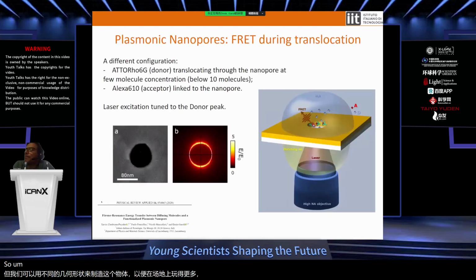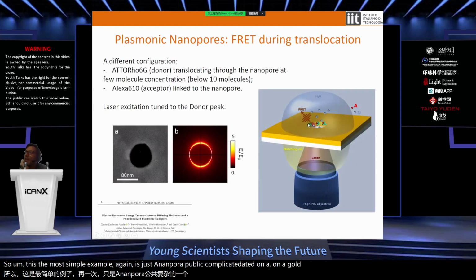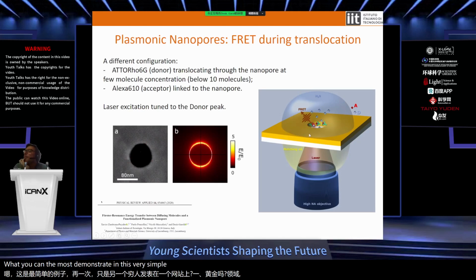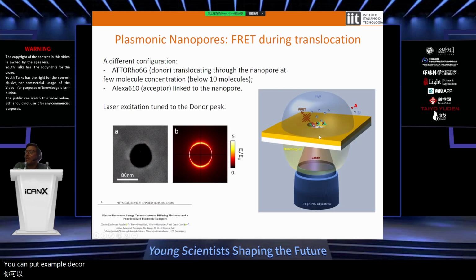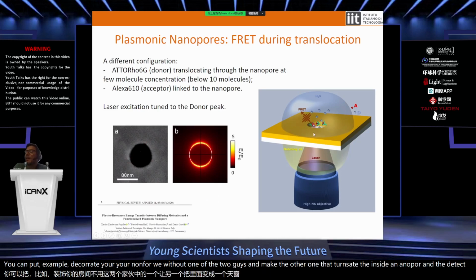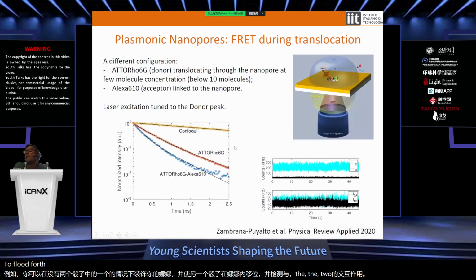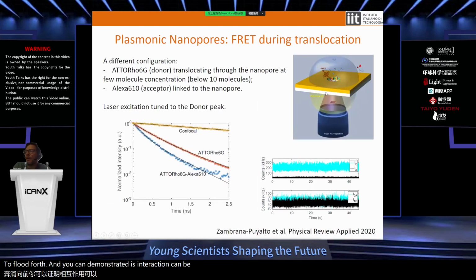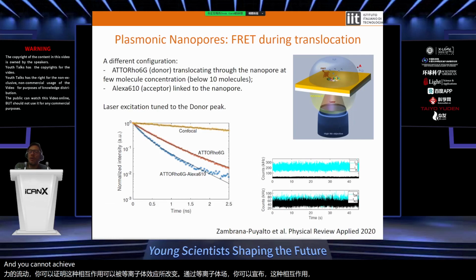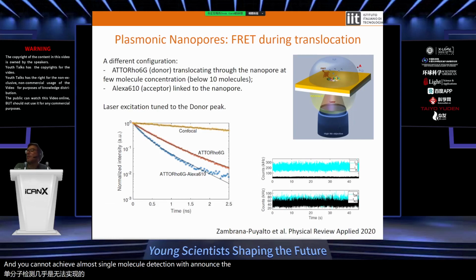The most simple example, again, is just a nanopore fabricated on a gold film. What you can demonstrate on this very simple platform is that, for example, if you want to play with Förster resonant energy transfer, with FRET spectroscopy, you can decorate your nanopore with one of the two dyes and make the other one translocate inside the nanopore and detect the interaction between the two fluorophores. You can demonstrate that this interaction can be modified by the plasmonic field. You can enhance this interaction, and you can achieve almost single molecule detection with enhanced resolution.